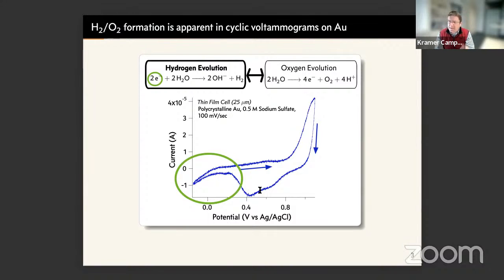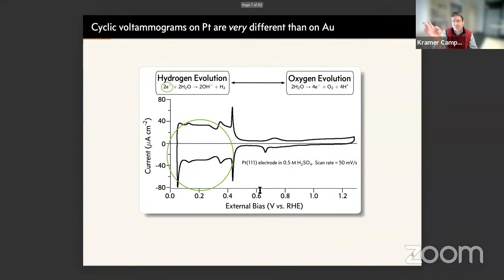Okay, but then I said, we want some empirical basis for understanding what material characteristics are likely to be important. So the next thing, of course, is to do the same experiment on a different metal, and in this case, a similar anion. This now is a cyclic voltammogram collected by Gregor on a platinum 111 working electrode, now in contact with a sulfuric acid electrolyte.